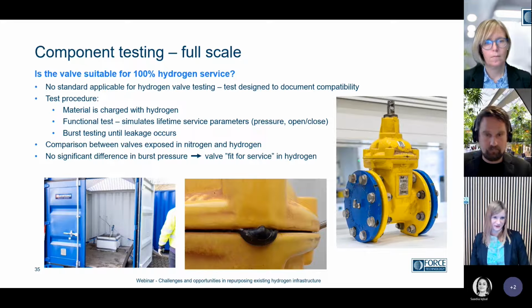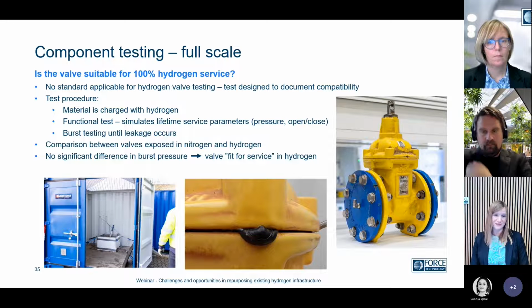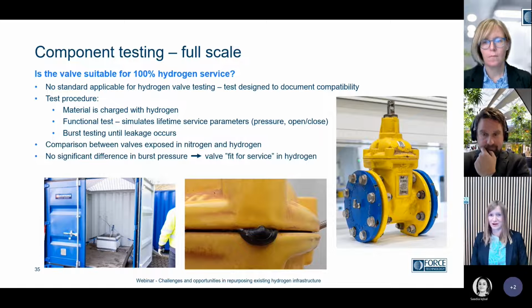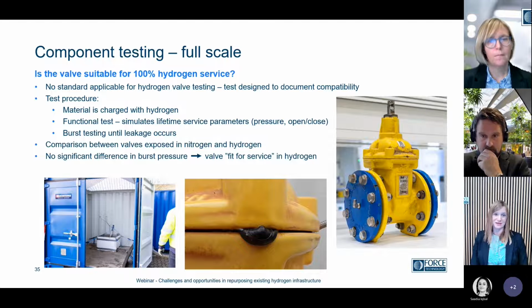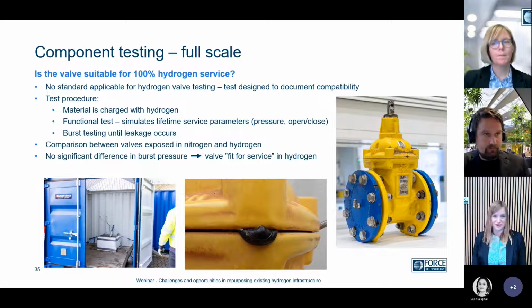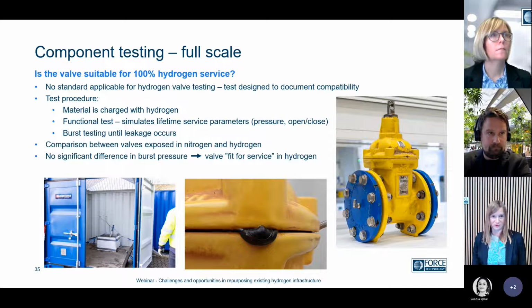This is an example of full-scale component testing we performed. What's interesting about this one is that the housing is made from cast iron. And as we saw previously, it's not permitted for use in hydrogen environments. But would it work? Well, this manufacturer did not have any applicable hydrogen standards. So we designed a special test like we have done many times before. The test procedure involved a charging phase simulating years of operation in hydrogen environments, ensuring sufficient hydrogen into the materials. Then we performed a functional test based on the lifetime parameters for this valve. So the number of openings and closings, the pressure cycles, and of course the service pressure. And then in the end, a burst test was performed until leakage.